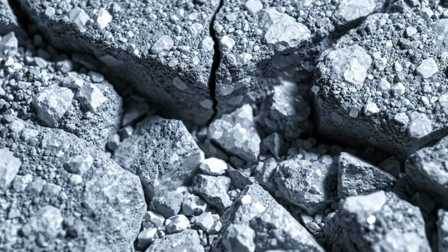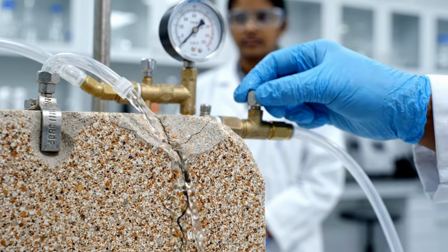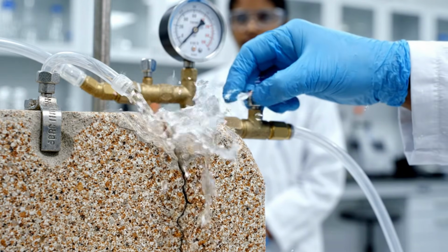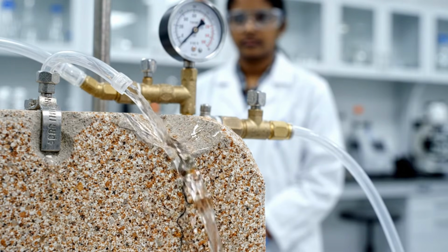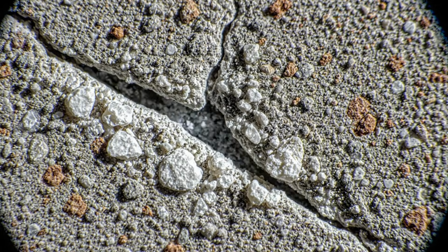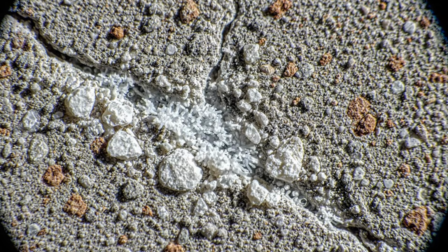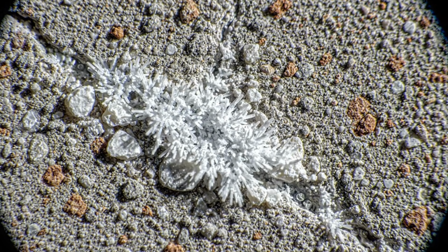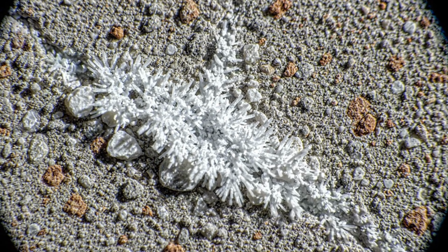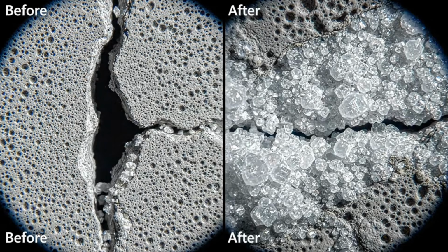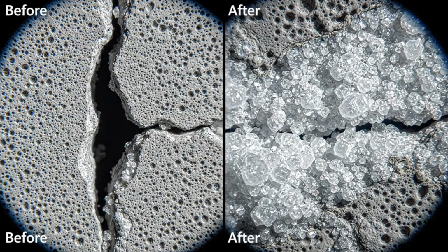Finding the clasts weaker than the surrounding matrix, the crack travels preferentially through them. Water seeps in, reacts with the clast fragments, and produces a calcium-rich solution, which recrystallizes as calcite, sealing the very crack that admitted the water. The defect intercepts the damage and repairs it.